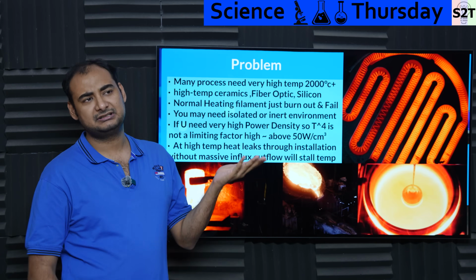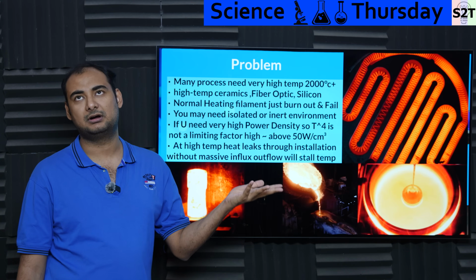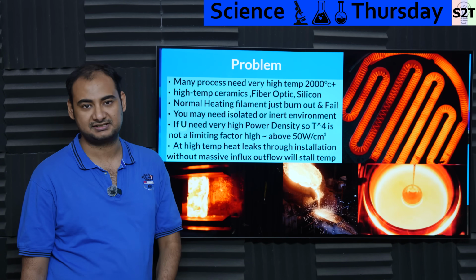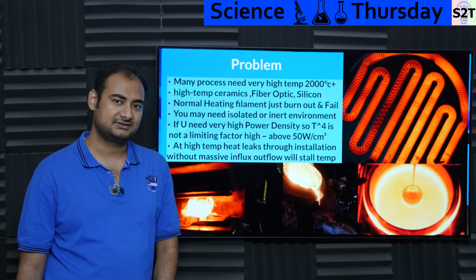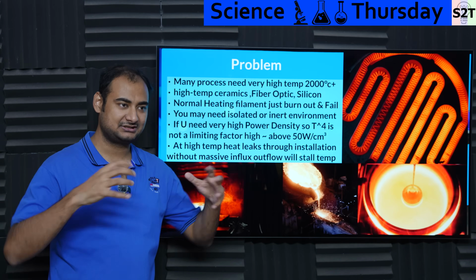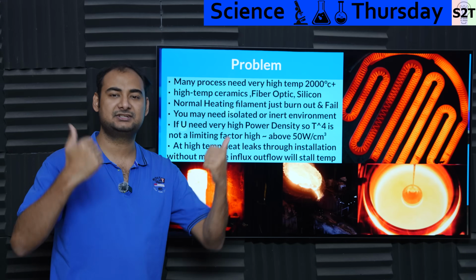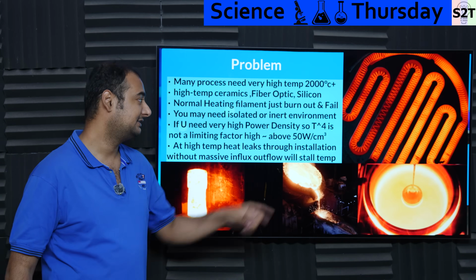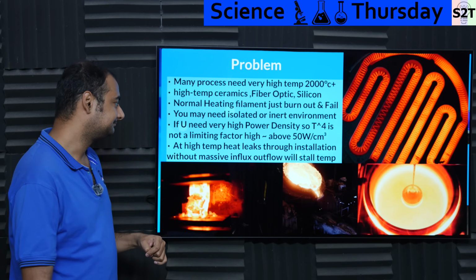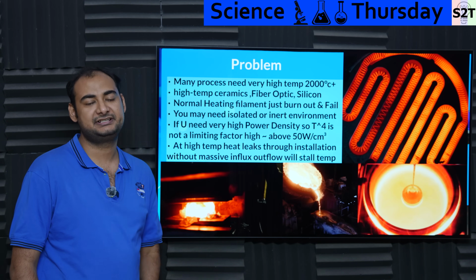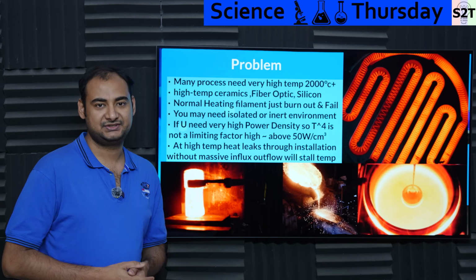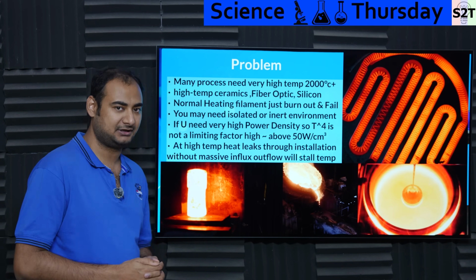How good your insulation is will define whether it's 70 degrees Celsius or 270 degrees Celsius, but it will not go to 1000 degrees Celsius, because the moment you increase the temperature, the push, the oomph that is going outside goes exponentially higher, to the power of 4. So that fundamentally defeats any low oomph device, meaning you have to dump a bonkers amount of power.